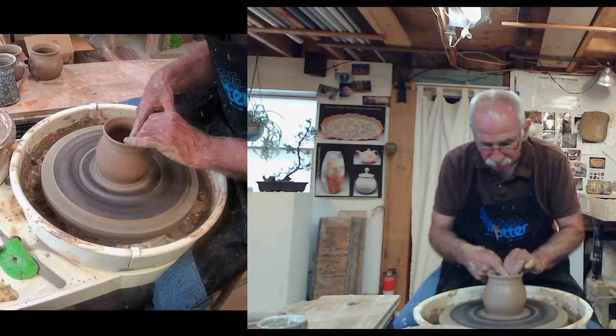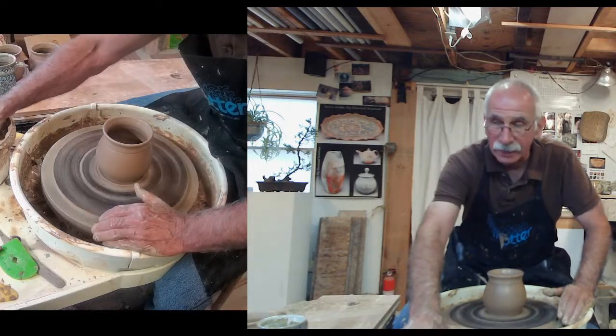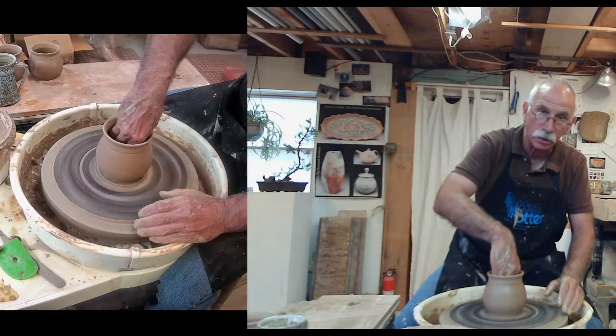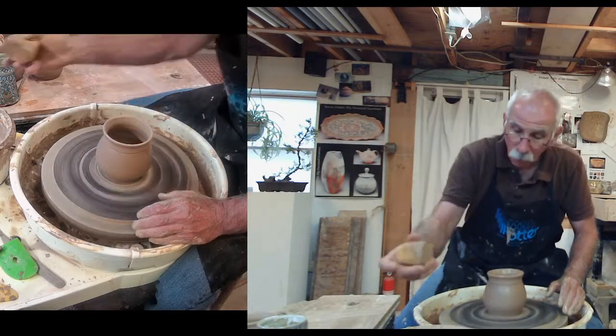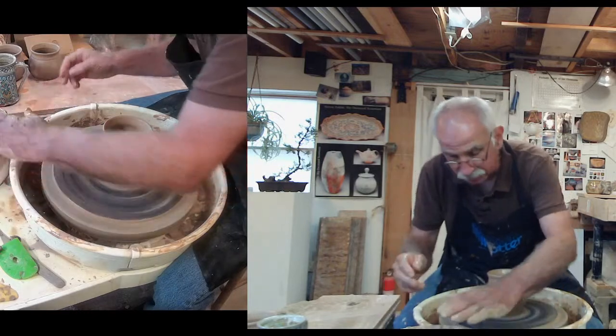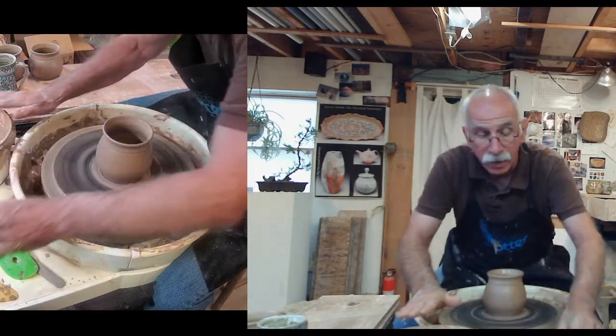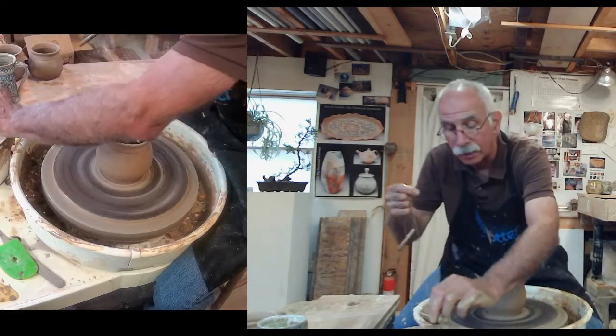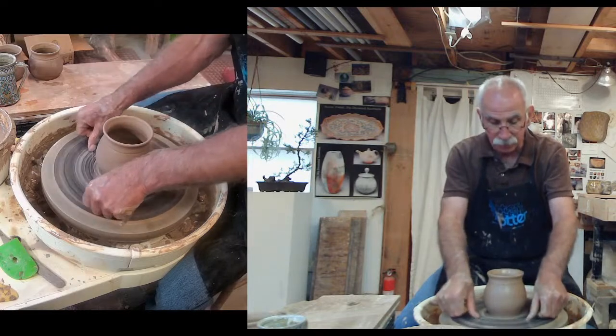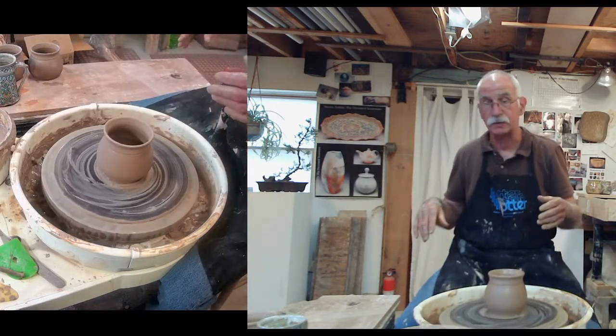Now, at that point, they come out, and I'm going to glaze it and then load it back into a kiln. And a glaze, by the way, is clays and oxides mixed with water, and you dip the pot in that solution, or you can have a spray booth and you spray them, or as some people like to do, is brush it on. I like the dipping method. Now, once I have dipped the pot into that solution of the mixture, they come out looking like a piece of chalk, and then I load them back into another kiln, and I fire them up to the 2,350 degrees Fahrenheit. Now, at that point, they are solid and vitrified, and they will be functional to use in today's modern conveniences.